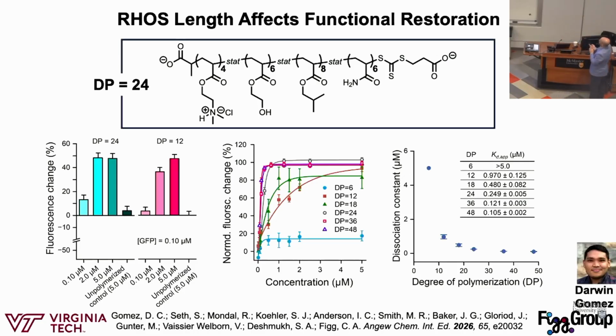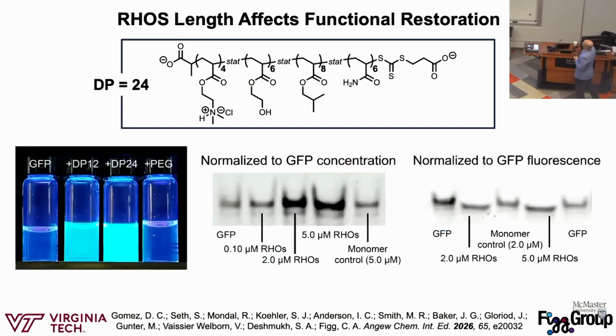This is about 100 nanomolar to ground us, and what that means: a bad antibody binds at around 1 to 10 nanomolar. Good antibodies are in the picomolar. We're in the range of a bad antibody, which is fine. You know, this is a single polymerization. You just mix the monomers, do the polymerization, get your polymer. We're getting 100 nanomolar dissociation constants, which is really interesting to us and incredibly scalable as well.